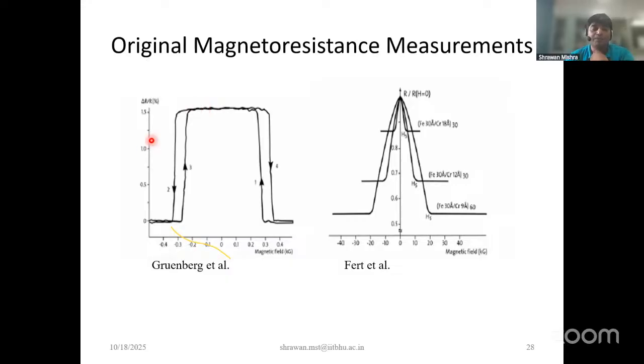When you are in the parallel configuration, you can say it's the on state, and when it reaches the anti-parallel, it's the off state. A very similar observation was made by Albert Fert, an independent observation from Peter Grünberg. They did almost simultaneous but independent work. And here he shows this using not only a spacer layer, but also demonstrates that by reducing the thickness of this spacer layer, you can actually amplify this effect. So this is a different observation from what Grünberg showed.